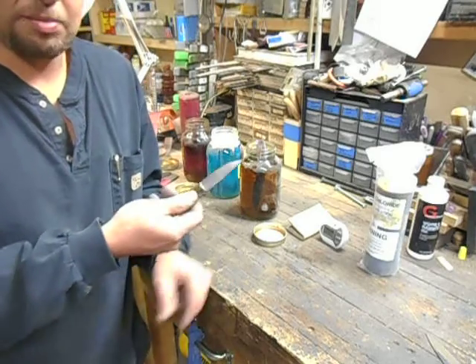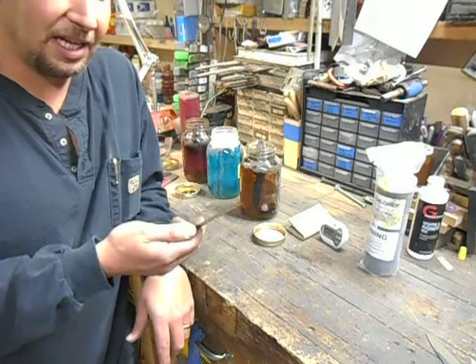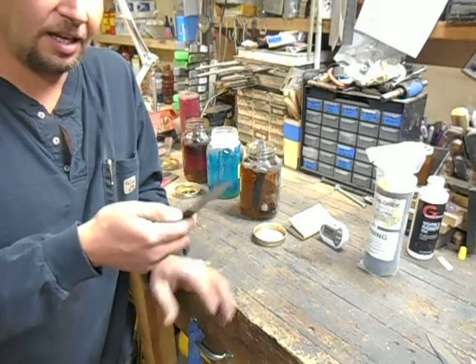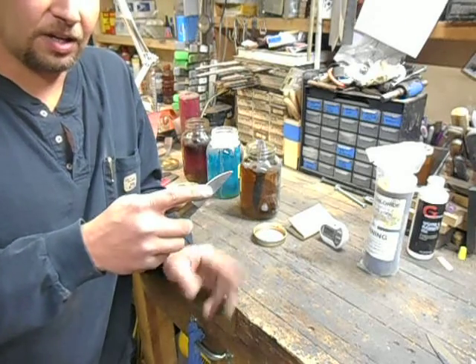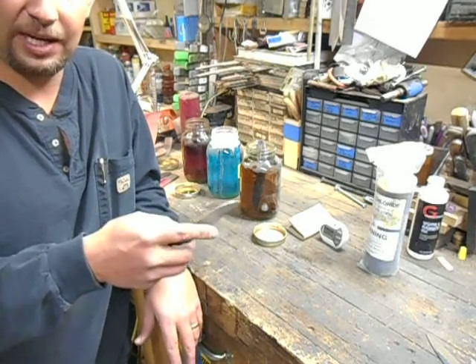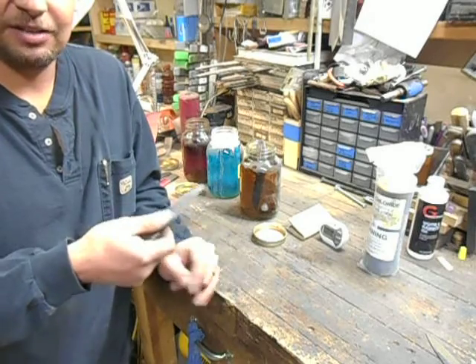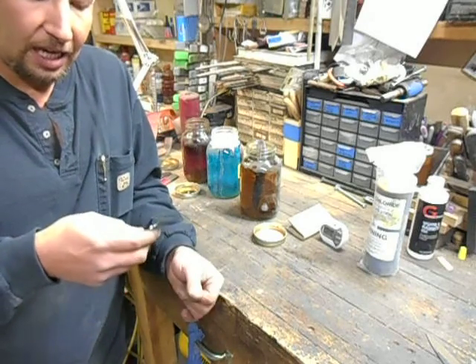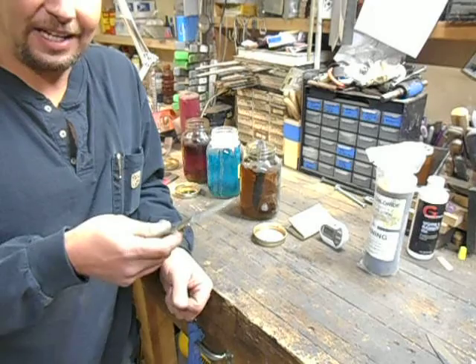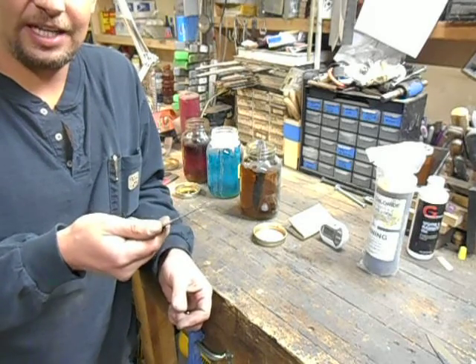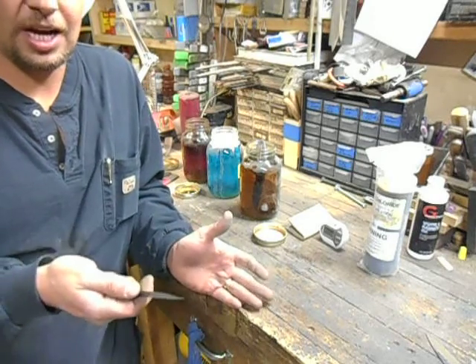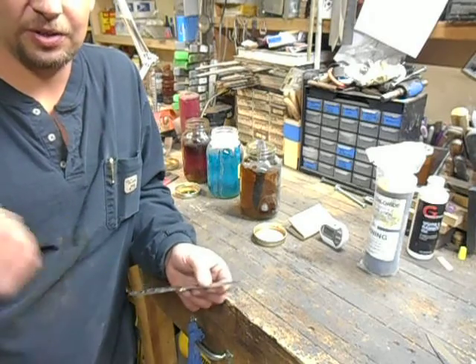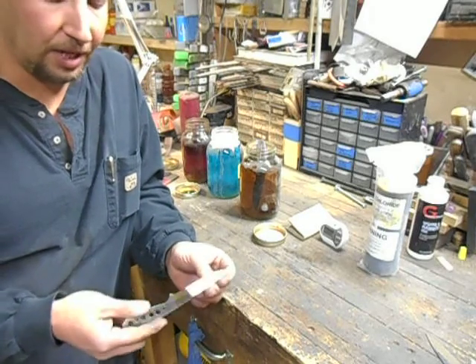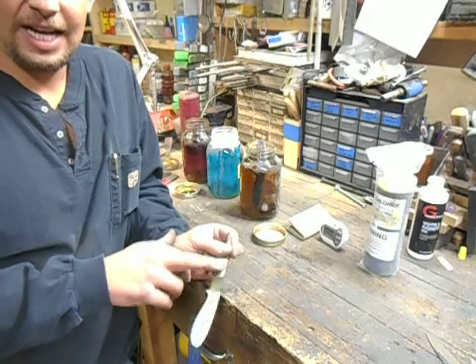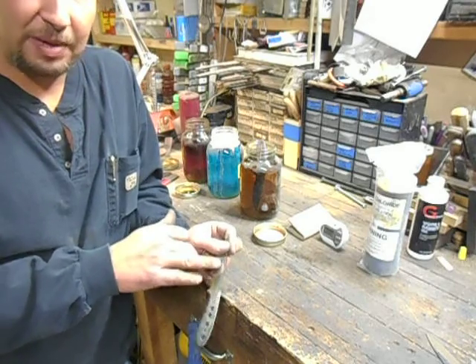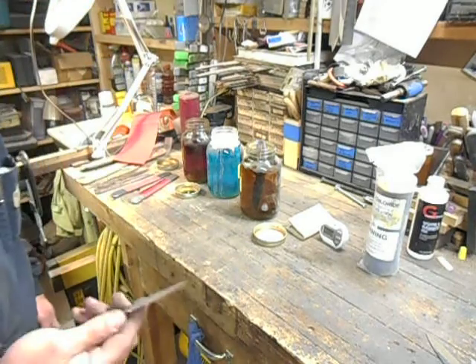Okay, but there's a whole bunch of different stuff that can go wrong with that blade after a successful heat treat during cutting in your bevels, sharpening, and finishing out that you might not know about. If you get a little too heavy-handed on this blade while you're grinding it, whether you grind it dry or if you run your grinders wet with water as a coolant like I do, you can overheat that edge. The edge especially, because it'll get thinner and thinner and thinner.